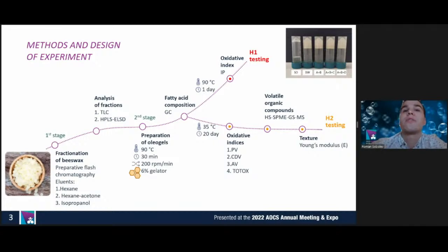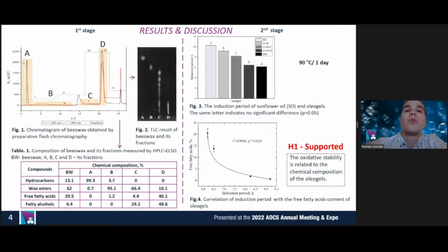To test the second hypothesis, the samples were stored for 20 days below the gelation temperatures. The evaluation of the accumulation of primary and secondary oxidation products, as well as the texture change of the samples, was carried out. Figure 1 shows a typical beeswax fractionation chromatogram. The isolated fractions are labeled with capital Latin letters A, B, C, and D. The results of the analysis of these fractions are presented in Figure 2 and Table 1.